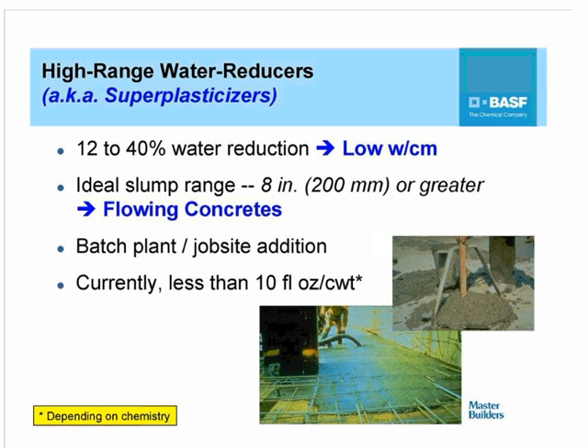However, with the newer technologies that are in place, much better control can be achieved with the addition of these materials at the batch plant. Now, with the new chemistries that are based on polycarboxylate ether, the dosages of these materials that are used in concrete currently will be less than about 10 fluid ounces per hundredweight, compared to the older technologies based on naphthalenes and melamines that would typically be used at dosages greater than 10 fluid ounces per hundredweight.